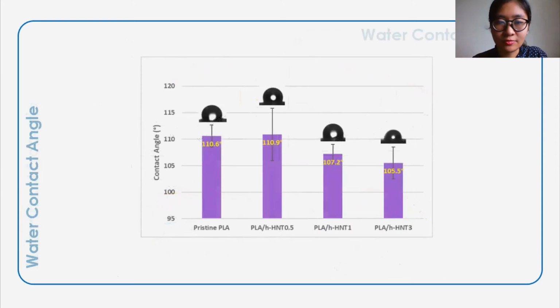Next is the surface wettability of electrospun fiber mats. So the average water contact angle was recorded. The electrospun PLA sample, known to be a hydrophobic synthetic polymer due to a lack of polar functional groups, exhibited a water contact angle of 110.6 degrees. The effect of increasing h-HNT content on the polymer matrix resulted in a slight decrease in contact angle.